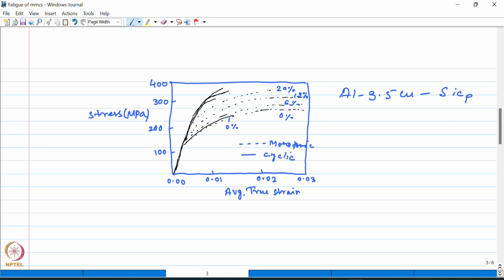Okay, for the cyclic loading condition, these are the corresponding curves. This is for 0%, then this one is 20, and then you have 6% and 12%. So you can see that the presence of the reinforcement particles makes a difference in the work hardening rate. It increases the work hardening rate in the material, both under monotonic as well as cyclic loading conditions, as you could see from this diagram for this particular composite. Okay, and the work hardening increase is more pronounced under cyclic loading conditions. That can also be observed from these curves for this particular composite.